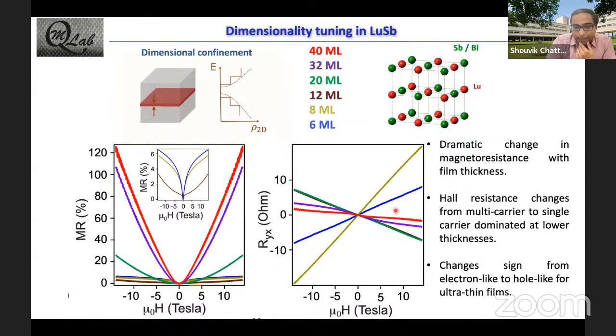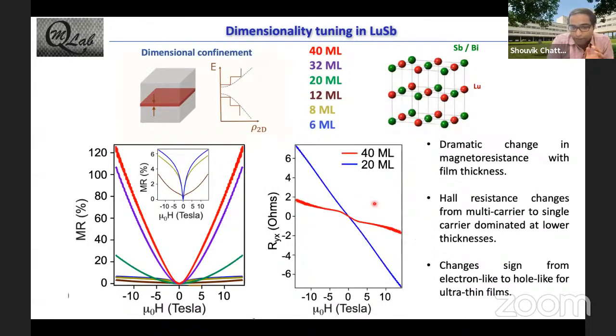Now, another aspect that I want to draw your attention to is in the Hall resistance. So what you see here is that it changes when you go from thick to thinner films, it changes from electron-like to hole-like behavior. Furthermore, I think this is more clear. When I go from the 40 monolayer to 20 monolayer, it goes from a nonlinear to a linear Hall-like behavior. So basically what you are seeing is that at a thicker film, you have a multi-carrier behavior from the Hall, which goes to a single carrier dominated behavior as you thin down your material system.